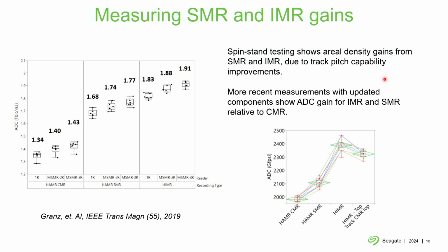And this is just data again, kind of old data, but it shows areal density. Sometimes we go terabits per inch, gigabits per inch, but hopefully it's not too confusing. And each of these are the areal densities for CMR, conventional, shingled, and interlaced. And the subcategories are 1 reader, 2 reader, and 3 reader. So for the experiment, we don't actually have heads that have 2 readers or 3 readers. In the experiment, we just do multiple read passes and average out the signals. So it just shows how you can significantly increase the areal density by doing these advanced recording schemes, and that multiple readers can really help in increasing areal density through that reader noise averaging.